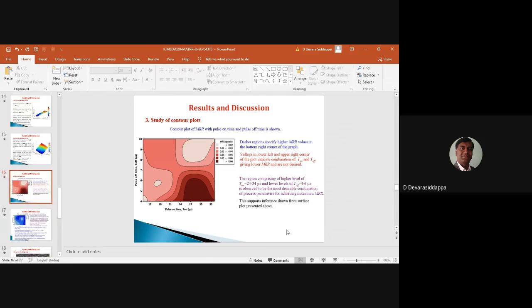In this case, you can see that the darker region, in the range of pulse on time of 24 to 33, and also the lower values of pulse off time, are desirable, whereas the shallow values and the lighter sections of the contour plots are not desirable, as they yield lower values of MRR, and darker regions indicate higher values of MRR. This observation, which we got through the contour plot, is also supplemented by the previous surface plot.